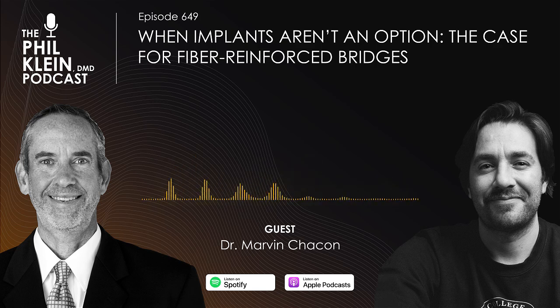So when a dentist gets into this and starts fabricating a fiber reinforced bridge, typically what should they expect as a lifespan? The average lifespan for a posterior bridge will be between 4 to 5 years, although there are documented cases of bridges lasting more than 22 years. And in the case of anterior bridges, we're looking at an average lifespan between 7 to 8 years. Wow. And then when you have a failure, what does the failure look like?